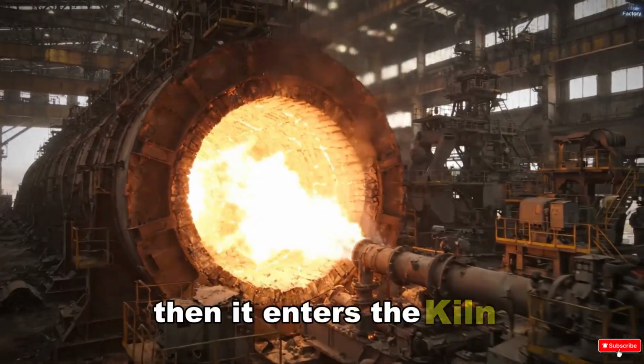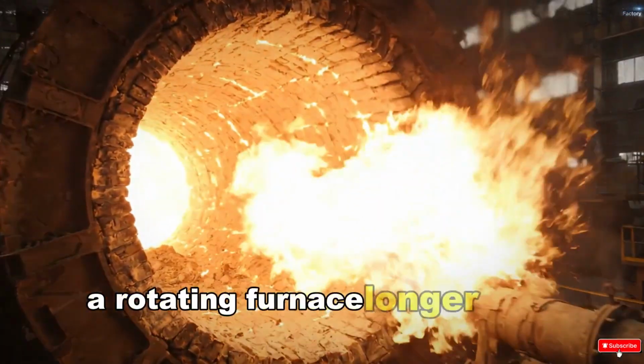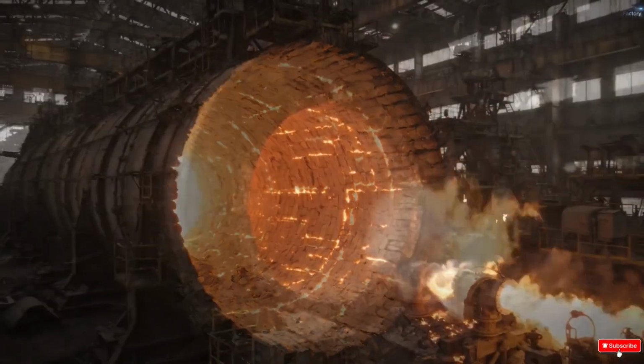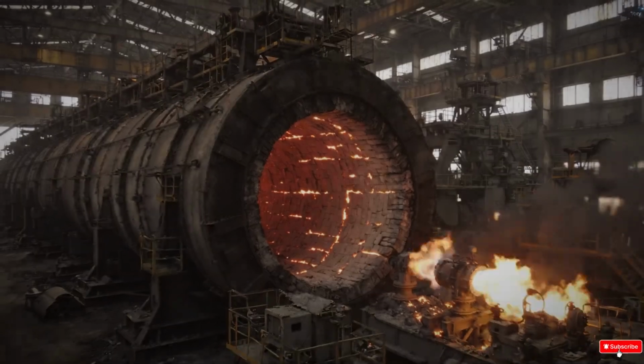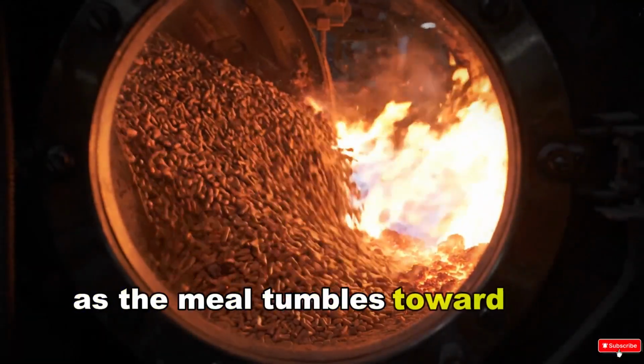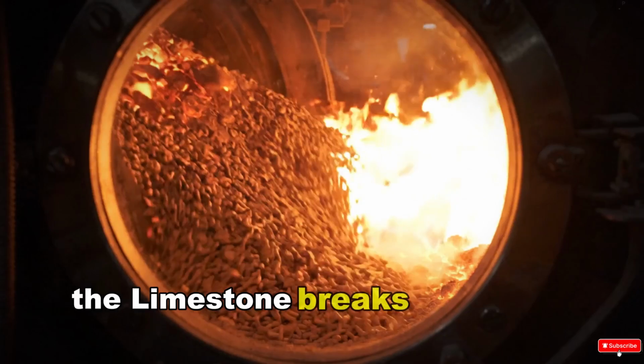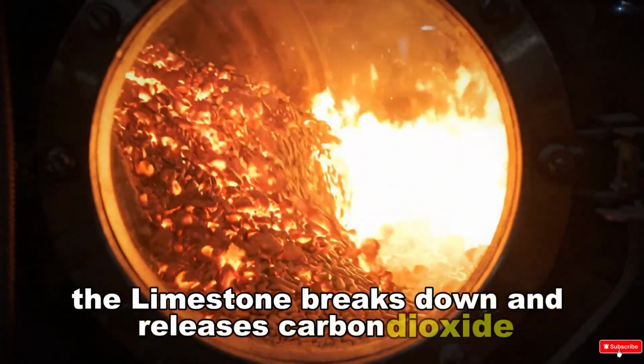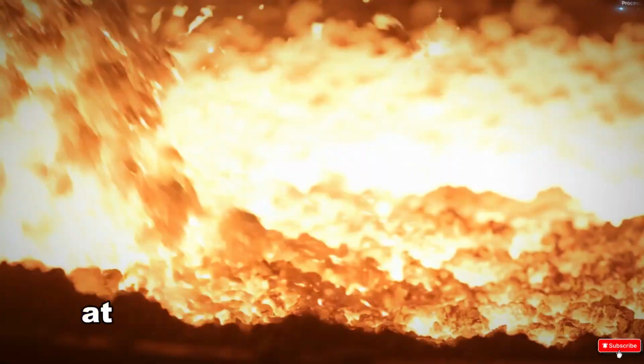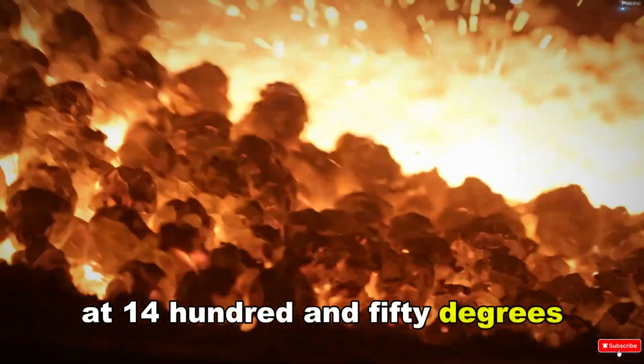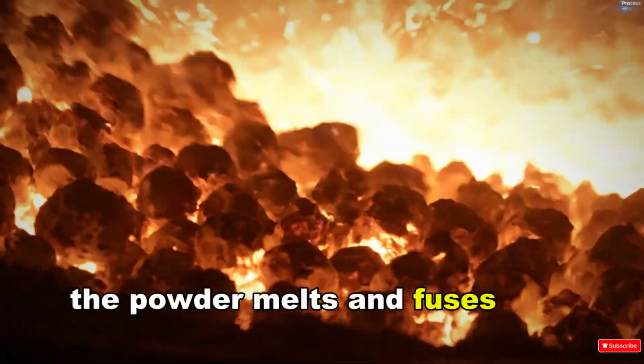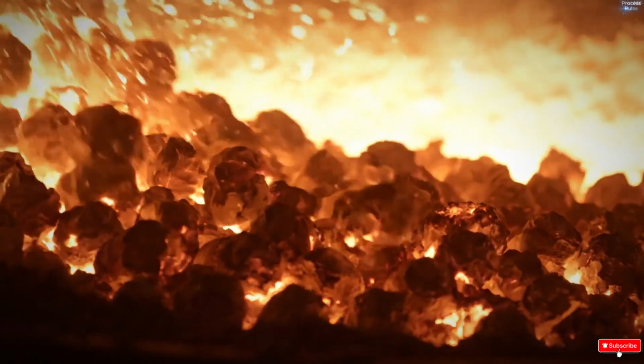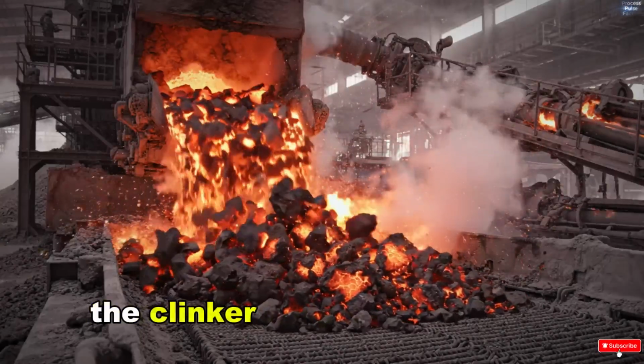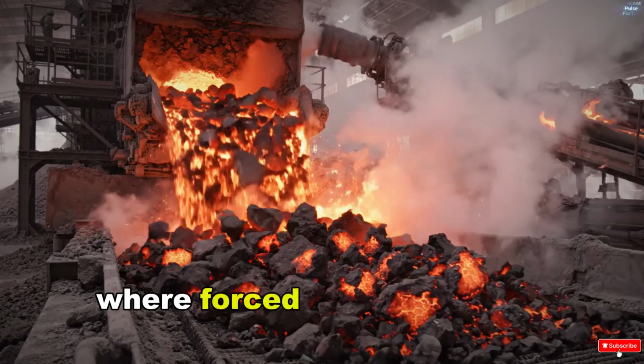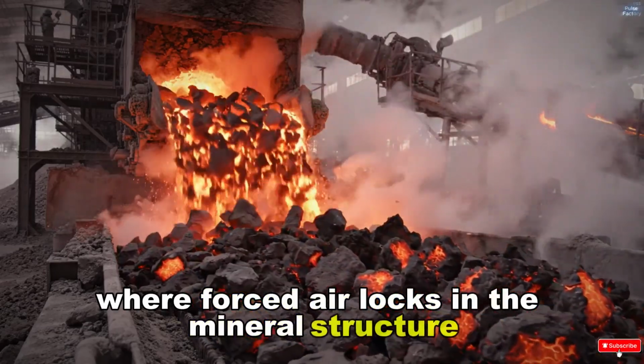Then it enters the kiln, a rotating furnace longer than most factory buildings. As the meal tumbles toward the flame, the limestone breaks down and releases carbon dioxide. At 1450 degrees, the powder melts and fuses into clinker. The clinker drops into a cooler, where forced air locks in the mineral structure.